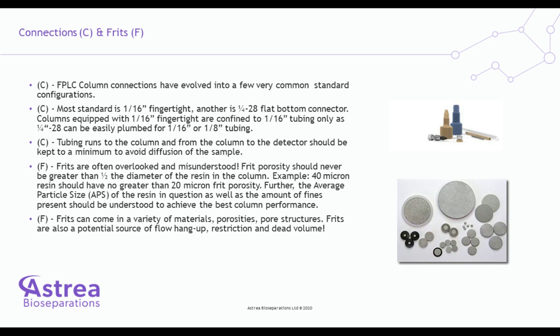And frits also come in different materials. They can come in polyethylene, they can come in stainless steel, some come in sintered glass, some come even in titanium, or even other materials, depending on what your running and storage buffers might be. We find, as a general rule of thumb, for most aqueous applications, polyethylene frits are generally well accepted and hold up quite well. They're also easily interchanged in the columns.